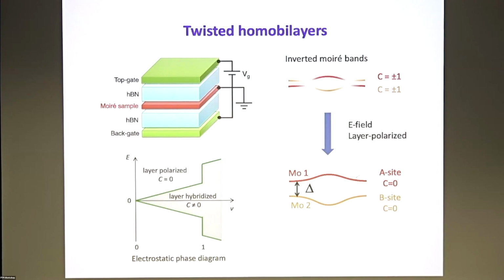In the small electric field regime, in this gray area, the system is in the layer hybridized regime, so the Chern number is non-zero for the bands. And if you apply a large enough electric field, you push all the electrons to one layer. It's called a layer polarized region, and in that case, the bands are non-topological, so the Chern number is 0 there. So it looks something like this, and the gray area actually expands with density, just because electrostatics requires that the more electrons you put in, the more electric field you need to polarize all the charge to one layer.